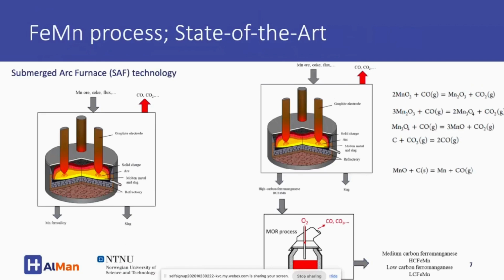Here on the right, you see the case for ferromanganese production. High carbon ferromanganese is produced in submerged arc furnace. And on the right, you see there are several reactions where we get manganese oxides reduced and we get to Mn3O4. In parallel, we have a not wanted or unwanted reaction, which is the Boudouard reaction, and some carbon in the process is lost to CO gas.